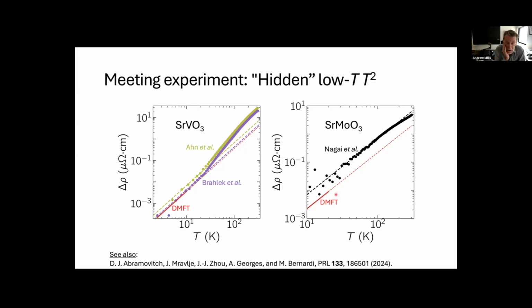Okay. But again, the striking thing about the comparison of these two pictures is that we see a T squared slope up to quite high temperatures in the data, presumably in the temperature range where the data is good, just with an offset, which is unlike strontium vanadate. So my question was really, how seriously should I take the agreement of slopes with DMFT?